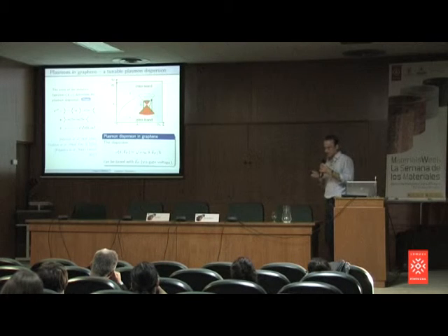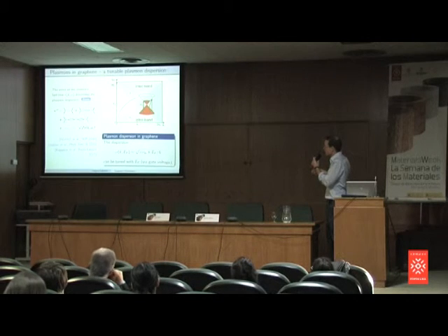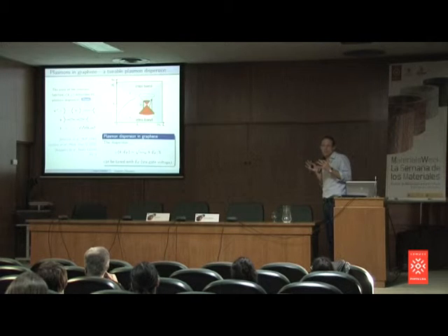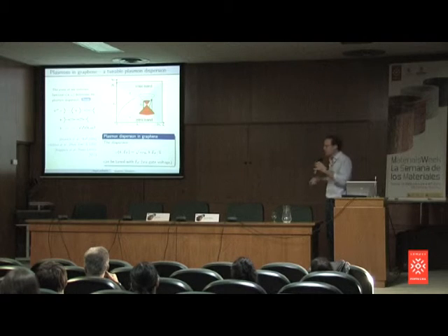And let's suppose we calculate this, and we can. Then this is a function of wave vector, which I plot here, and of frequency, which I plot here. And when this thing here is 0, then the interaction between two electrons is strong. And this is where we get a plasmon, because then they will go together. Now I plot this, and, well, I get this red curve.